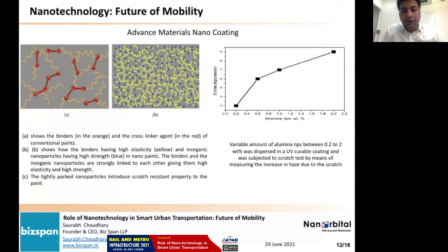So with these advanced techniques for nano paintings, you can see how it impacts. This A section is the conventional one. So you can see the binders in orange, and the cross linker agent in red, of the conventional paint. And then you come to the nano coatings with the advanced materials. So you can see the binders having high elasticity, the yellow part, and the inorganic nanoparticles, the blue ones, are strongly tied up. So these linkings give them high elasticity and high strength. And this is tightly packed, so this can also be scratch resistant.